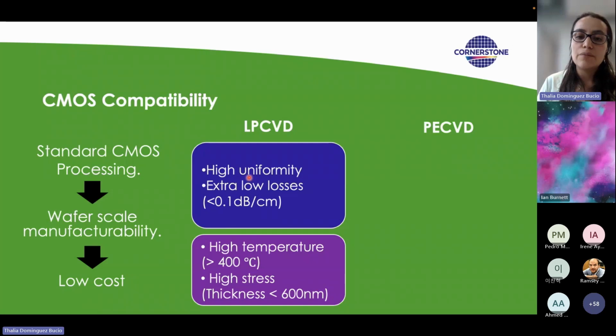The other problem that LPCVD silicon nitride has is that because it's deposited in a furnace at high temperature, and you deposit on both sides of the wafer, you tend to get a very high stress. So typically speaking, you cannot deposit silicon nitride layers thicker than 600 nanometers. So you're limited to a thickness of 600 nanometers unless you do some more complex fabrication processes.